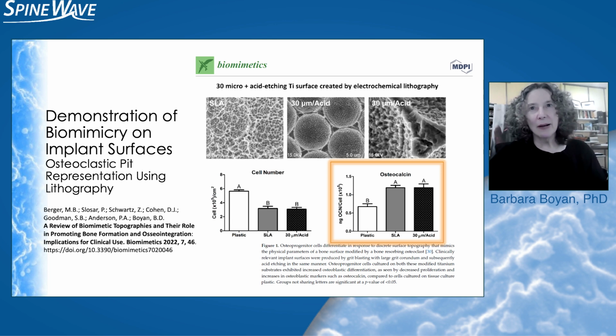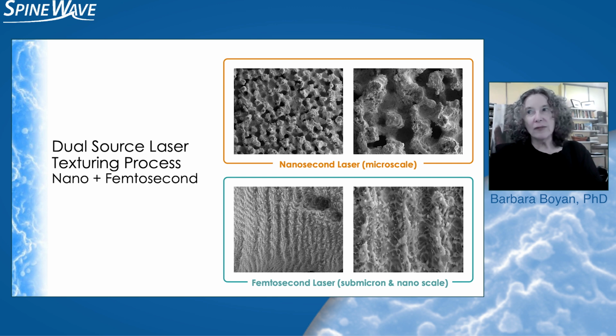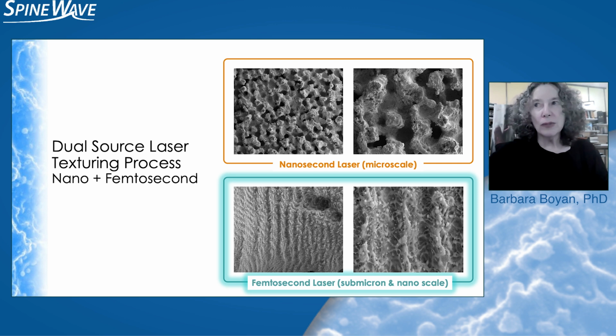Well, that's great. But what if we could get a surface that looks just like that surface that is at the basement of an osteoclast resorption pit? And I'll be darned if SpineWave didn't do it. So here we are. We are looking at the surface of a titanium aluminum vanadium disc, and it has been treated with the nanosecond laser, so nanosecond pulses of laser. And you can see how we get this kind of morphology. And if we then add on a femtosecond laser, even faster little pulses, all of a sudden, what we're looking at are these ridges. And boy, if they don't look like the basement of that osteoclast resorption pit, I don't know what does. So we've created a structural element on a metal surface that is a real biomimetic of the biology.